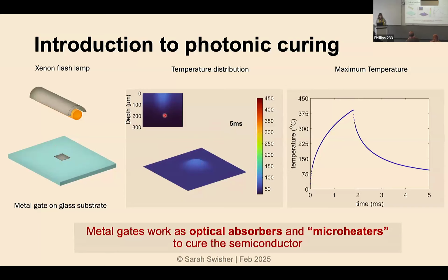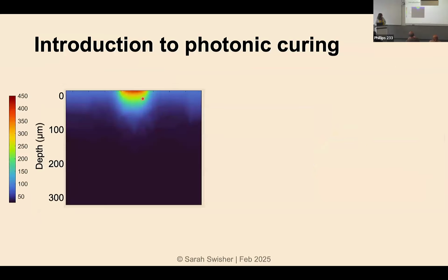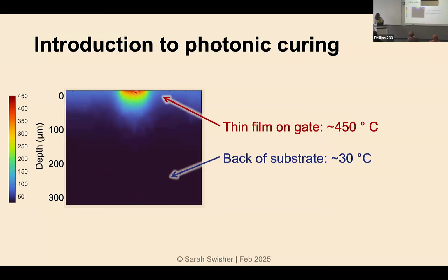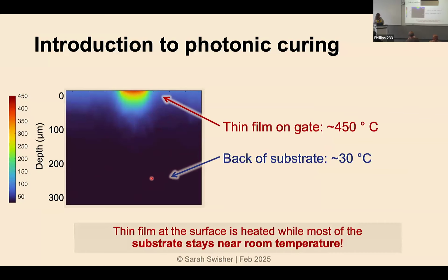So if we take this cross section, this is what the temperature profile looks like as a function of depth into the substrate. So this is modeling a metal gate on a glass substrate. So you would have your semiconductor material up here on the top. And what we can see is that a very, very small portion of the substrate is reaching this very high temperature, but it very, very quickly drops off, and you've got this temperature gradient so that at the back of the substrate, you're sitting near room temperature. So this is the other key point that I want you to take away from this, is that the thin film is heated while most of the substrate below is not.